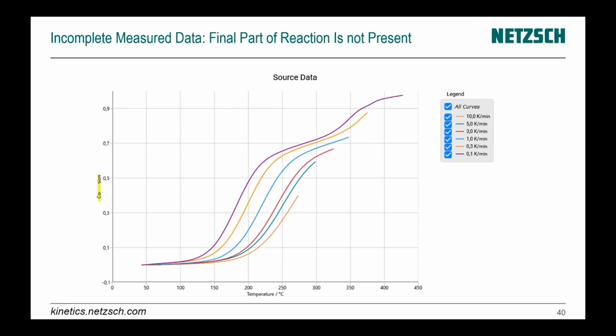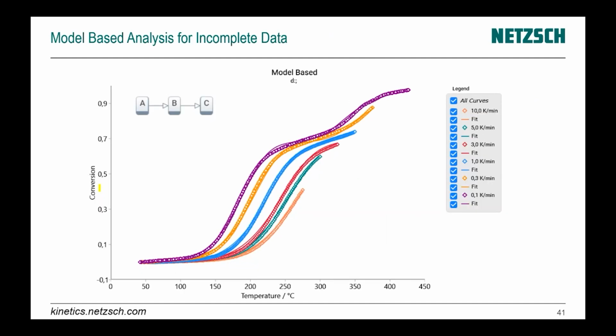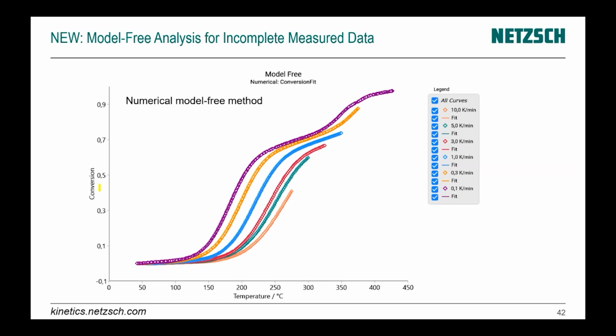This data, actually, they are nice and they could be analyzed by model-based methods. It was so up to now and in previous versions of Kinetics Neo software, but now we are able to make a model-free analysis of this data by numerical model-free methods. Here we use 6 curves for calculation of activation energy, and here we use only 2 curves. For the last part, even here is a very, very nice fit. The activation energy for this last part could be incorrect because the model-free analysis requires more than one curve which is measured at different heating rate or at different conditions.